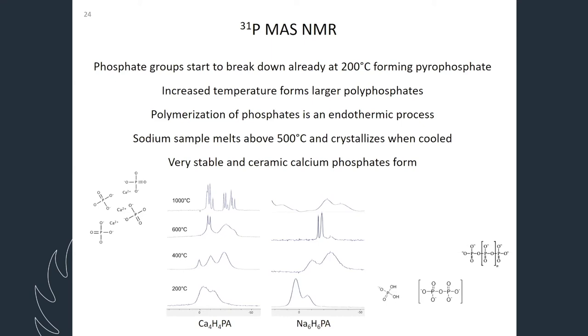So those phosphate groups in the phytic acid molecule, they have started to break down and then fuse together. So we get two phosphates fused together into a pyrophosphate. And when we increase the temperature to 400 degrees, we can see that for calcium, we still have the original phytate there. We have some pyrophosphate, but we have also started to get higher polymers with more than two fragments binding together in a polyphosphate chain.